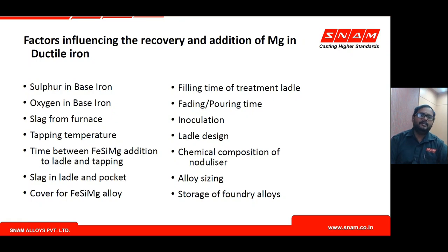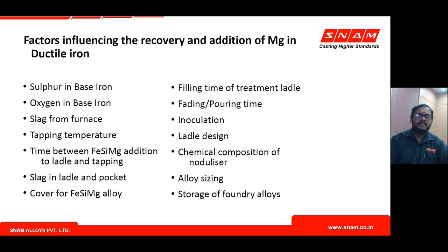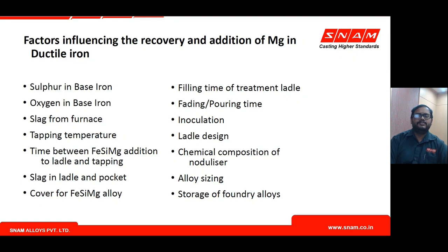Regarding storage of foundry alloys: these materials are not highly hygroscopic but do pick up some moisture when exposed to it. Moist material added to liquid metal can be catastrophic — the moisture becomes steam, a strong oxidizing agent, and reacts with magnesium to form undesirable compounds.